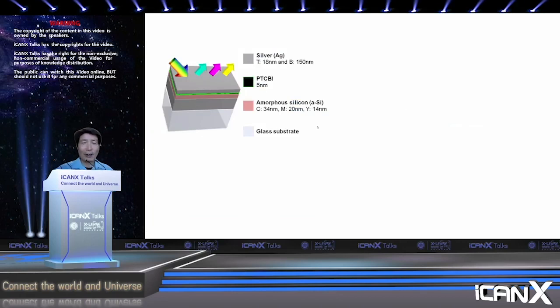So here, come back to the same structure again. You see that we use amorphous silicon and silver, right? There's one material I didn't discuss at all. It's PTCBI. It's only 5 nanometers. This is an organic semiconductor, but in this colored structure, it doesn't actually serve much purpose. The only purpose it serves is that we want to produce a thin and smooth silver film. So this PTCBI magically helps that. And here we use an 18 nanometer silver, and it's smooth.